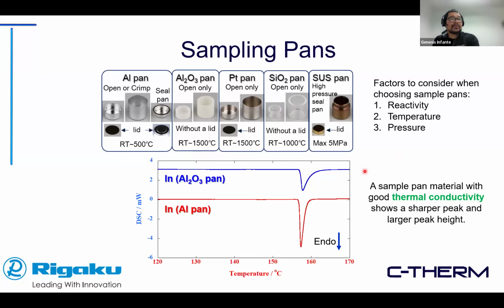Another important factor to really look into is the consideration of thermal conductivity. So different materials will conduct heat differently, and the DSC detects the change in the case of a thermal event. So if a thermal event occurs in the material or crucible, that heat has to be somehow detected by the detector in the test chamber. Depending on the pan that you use, there's going to be different rates on how that heat is transferred from the pan into the detector itself.